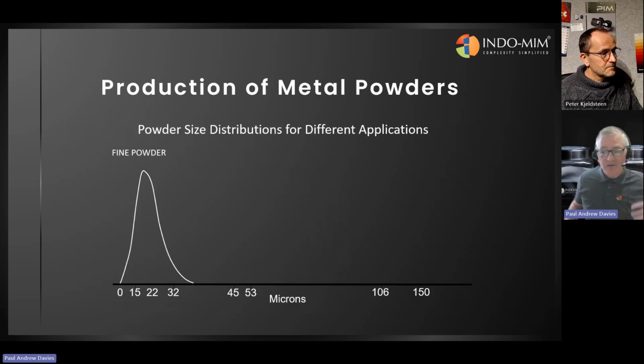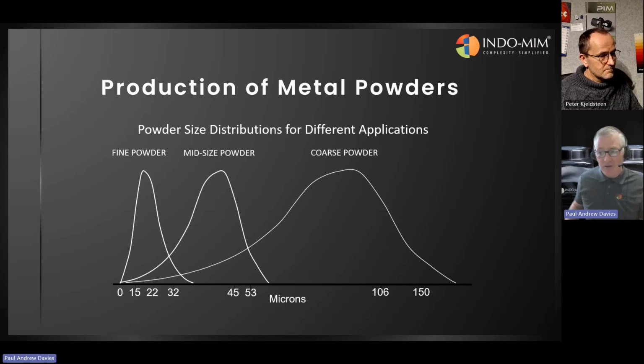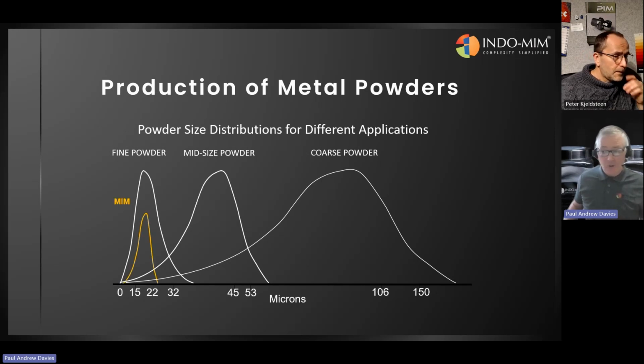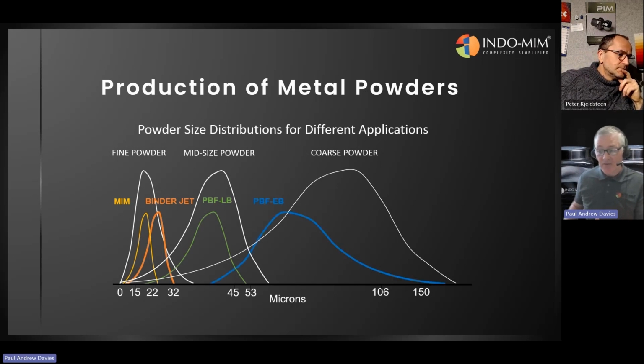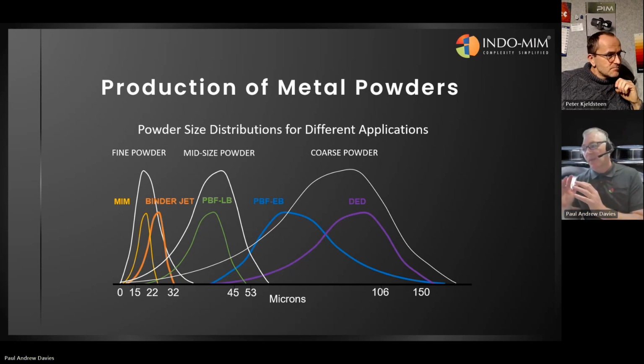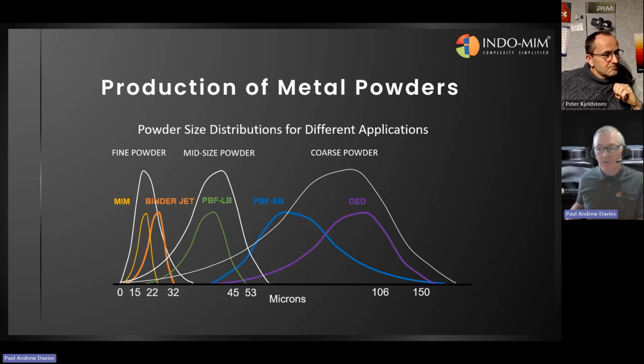So we can manufacture fine, mid-size or coarse powders, and they all have their challenges, I suppose. But of course, it's really about creating the appropriate atomizing configuration and process parameters to make powders for metal injection molding, binder jet printing, laser powder bed fusion, powder bed fusion for electron beam, or DED as well. You have to set your atomizing geometry and process parameters to target the right market that we're involved in. Generally, Indo MIM are interested in fine powder for MIM, binder jet, and powder bed fusion, and then eventually we'll adjust atomizers to create coarser powders as well for DED, E-beam, and HIP.